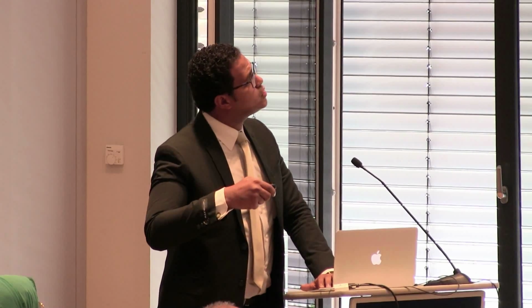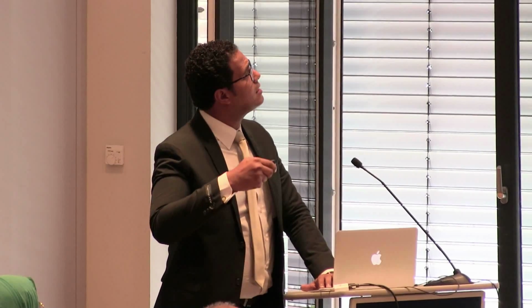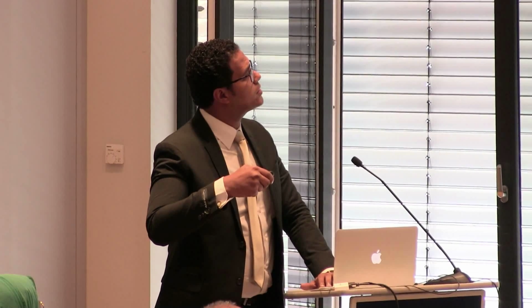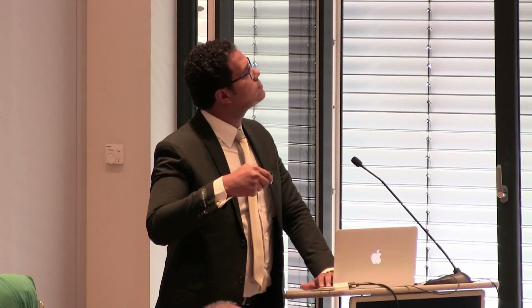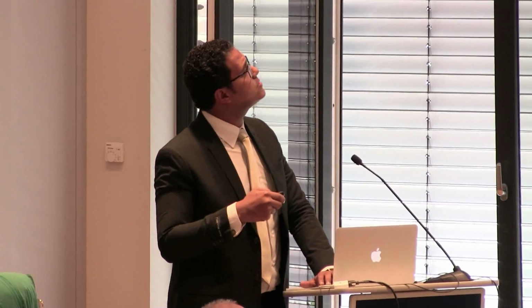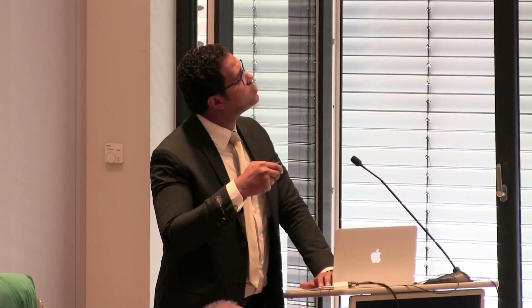This is the size range distribution of our particles, mainly around 7 nanometer, size distribution by zetasizer. This is the charge of our particles, minus 12.3.